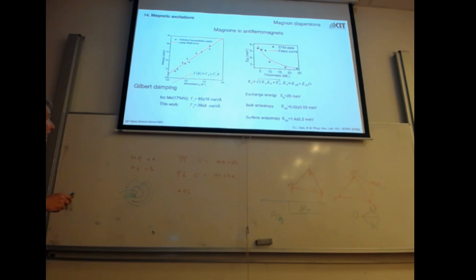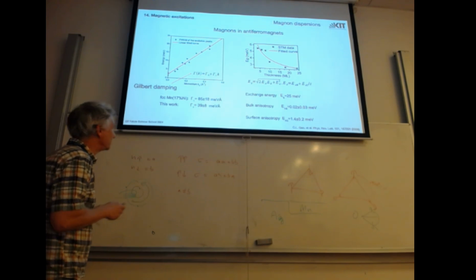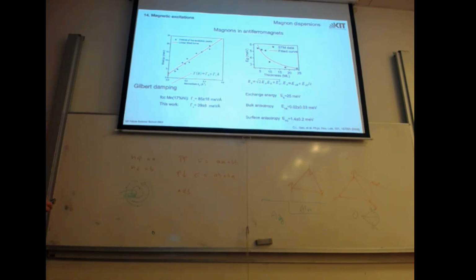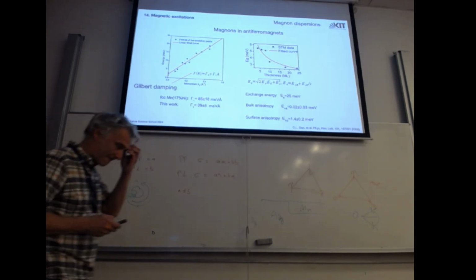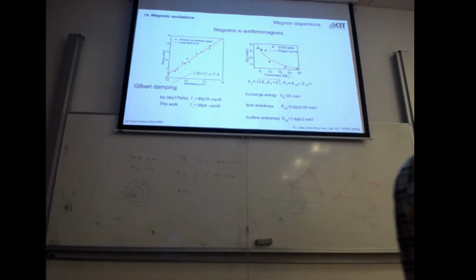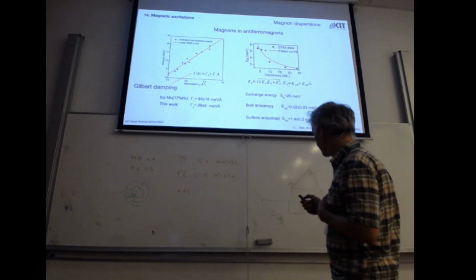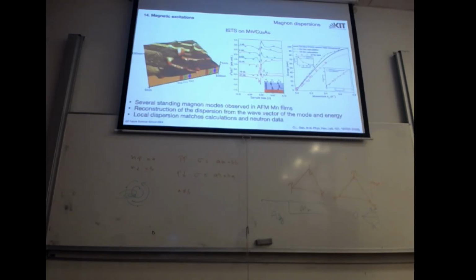So our gamma 1 is about 28 millielectron volts per angstrom, and neutron scattering was higher, so the damping was higher, 85, but keep in mind this is 17% doped with nickel, so maybe the damping is also different. So also lifetimes of magnetic excitations can be measured. And even more so, you see that our dispersion does not really stop at 0. So the 0 mode does not live here at 0 energy, it's at a bit higher energy.